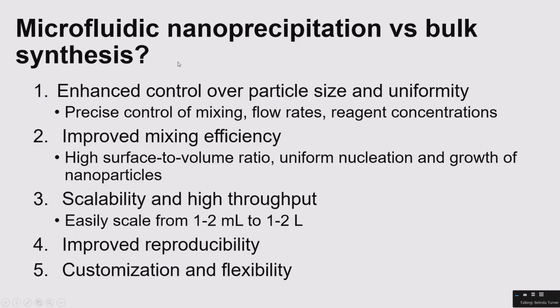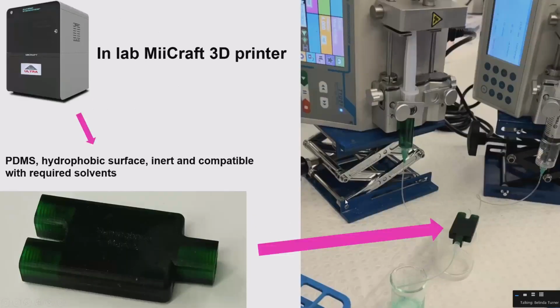So what's the benefit of using microfluidics versus bulk synthesis? So we get enhanced control over particle size and uniformity through the precise control of mixing, flow rates and reagent concentrations, improved mixing efficiency due to the high surface to volume ratio, uniform nucleation and growth of nanoparticles. And for us, it's quite scalable and high throughput, so we can easily scale from 1 to 2 mils to 1 to 2 litres. And because of the enhanced control over the mixing, we've got improved reproducibility as well.